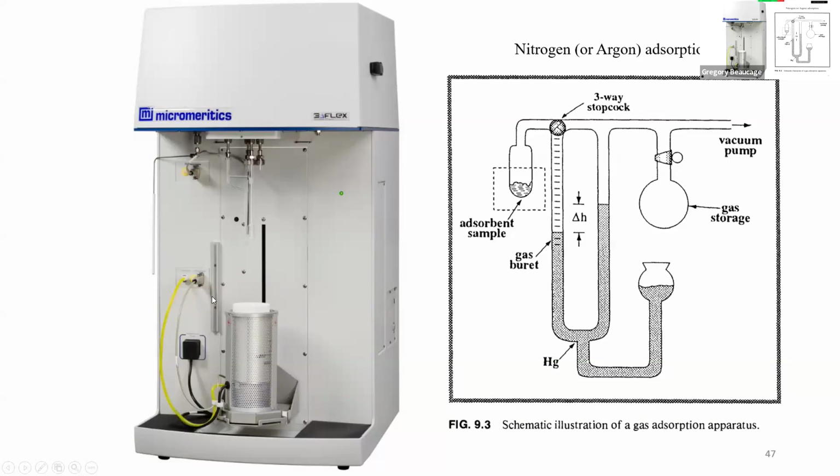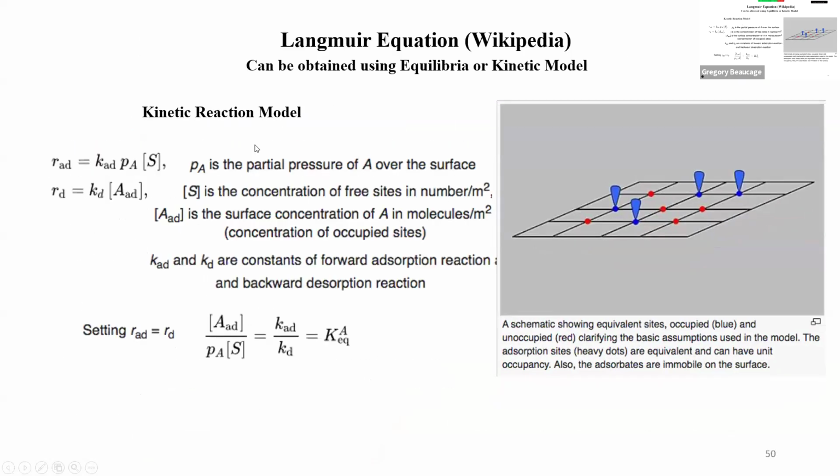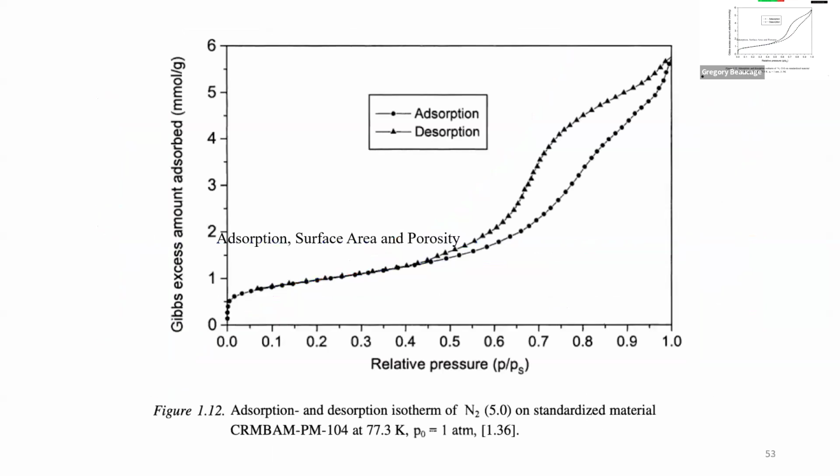So you put liquid nitrogen in the dewar and stick your particles in there. It's going to condense the gas on them. Then you wait for a while to reach equilibrium, then you pull it up and it degasses. That's basically the idea. So when you analyze that, you'd see there's a change in the surface coverage with the pressure that goes into this. So you're going to get a curve like that.